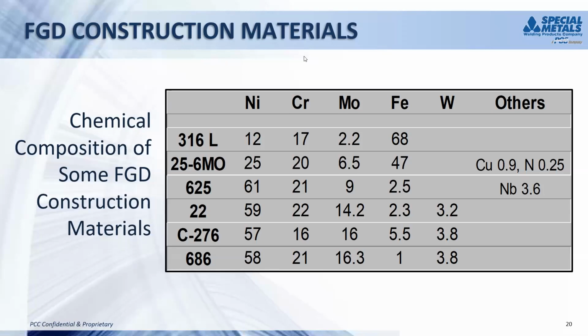Whereas the higher alloys at the bottom, 22, C276, and 686, have 14 to 16% molybdenum. And if you'll note, they also contain 3 to 4% tungsten. And tungsten has an additive effect with the molybdenum. So the relative resistance to localized attack is the combination of those two elements. So obviously they have much greater resistance to localized attack than the lesser materials.